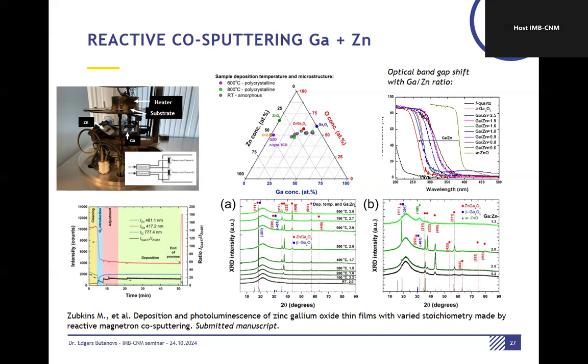And what is nice with our system is that we have so-called plasma optical emission spectroscopy. So we can monitor the zinc and gallium proportion in the plasma, and we can do a feedback loop to the power controller. So in real time, the computer adjusts the sputtering power depending on the composition of the plasma. So it gives very nice uniformity in the films. And this is a very nice state-of-the-art tool for co-sputtering of films. This we have already published in the spring, I think.